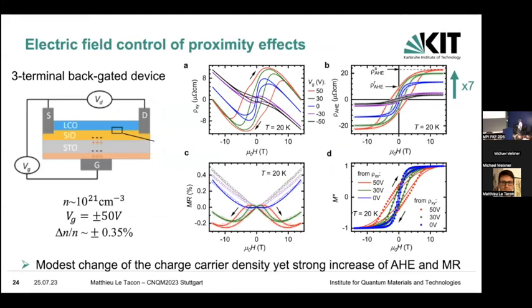The next step, having found that, we thought we should try to actually get our device, and this was a bit of work, to make some gatings of them and to try to dope the iridium layer by field effect. When we do that, we can estimate roughly the change with 50 volts of a very modest change of the relative charge carrier density.